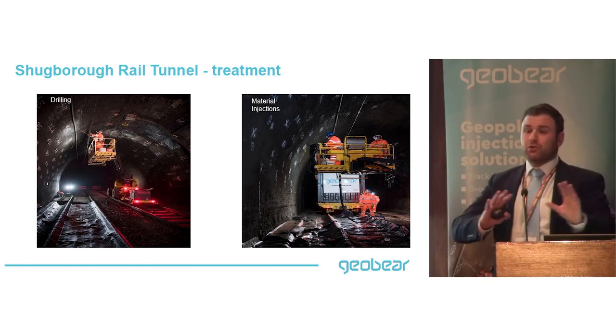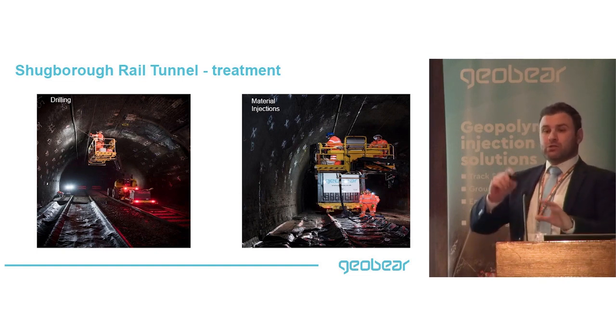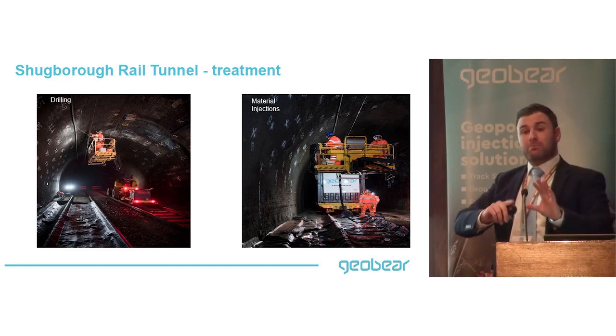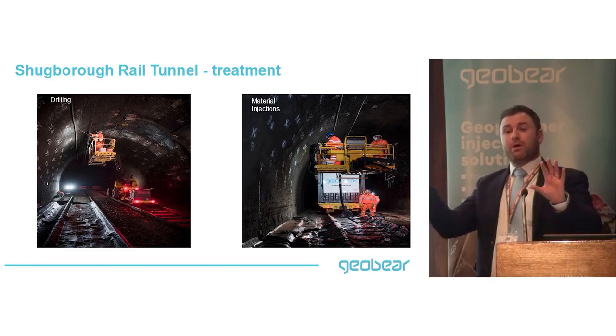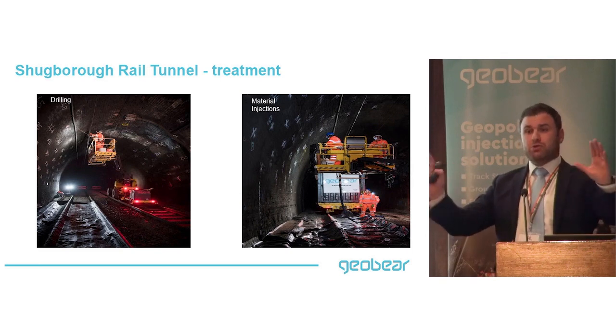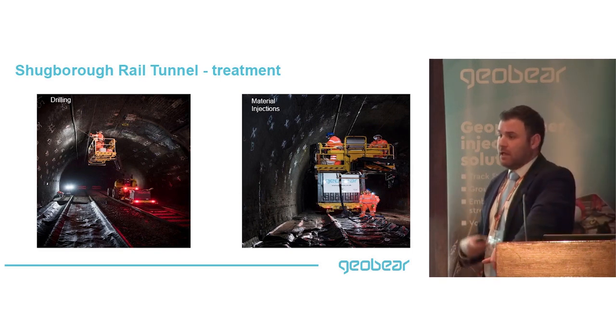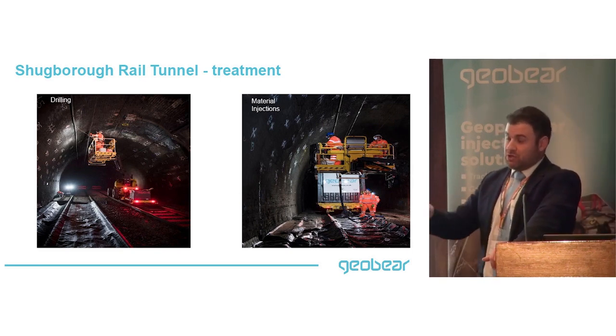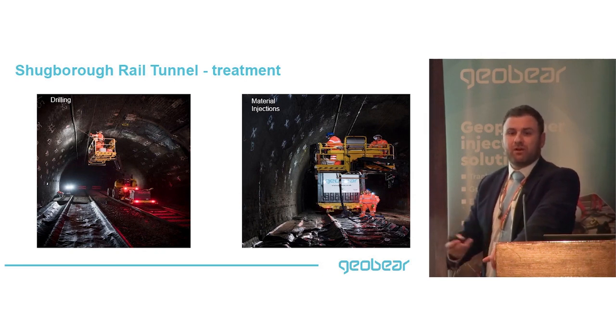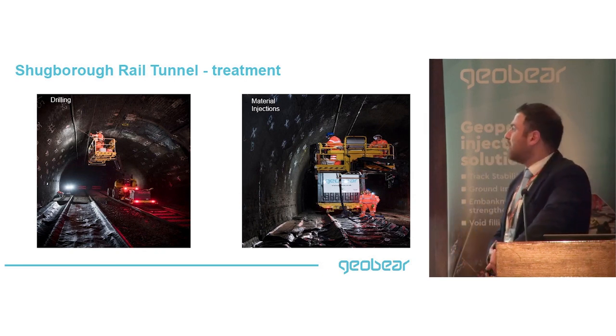What we've done to ensure we fill everything properly is inject in one location and observe how the polymer migrates to adjacent locations, just to make sure we fill that space, and making sure adjacent holes act like a release valve so you don't build up any extra pressure behind the tunnel lining.